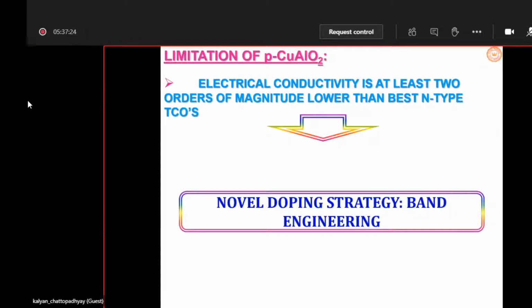The question is why? Actually, the presence of oxygen is itself detrimental, because oxygen, as you all know, is a highly electronegative element. Whenever a hole is present, it faces Coulombic attraction, and it's very difficult to move it. You need a large electric field to move the hole from the influence of oxygen. So along with the valence band dispersion, if you somehow could decrease the electronegativity of the anionic site, then it will lead to higher mobility and better electrical properties of this P-type TCO.